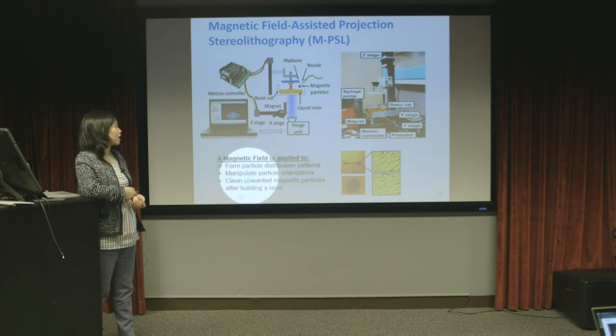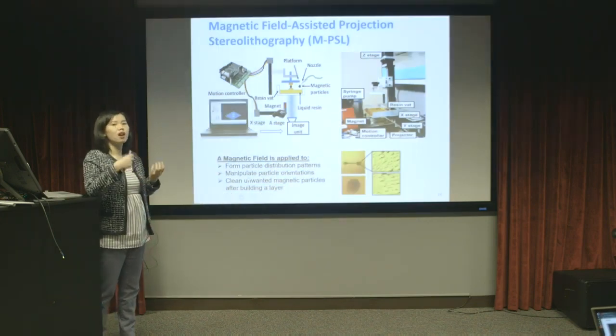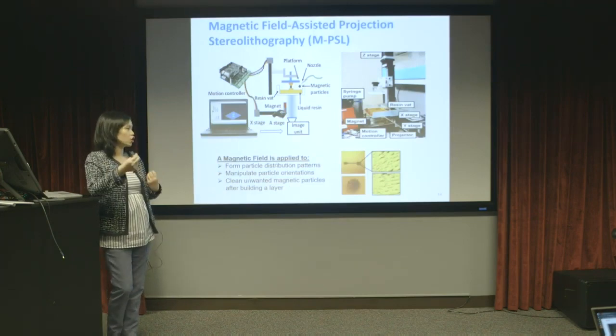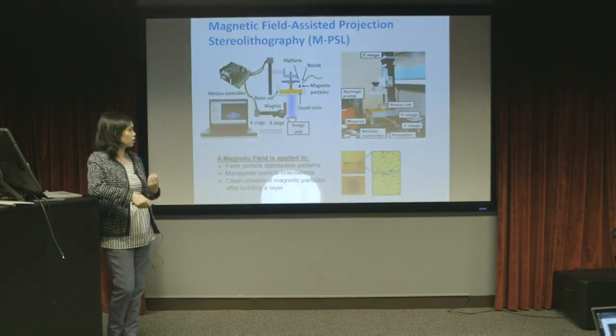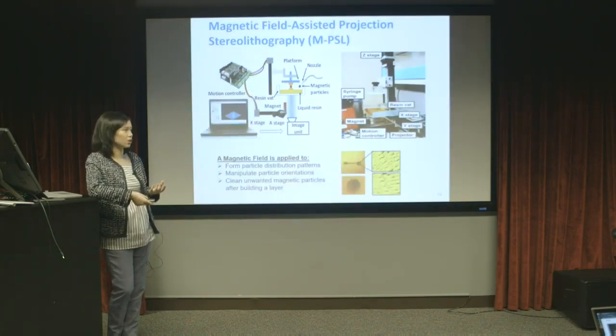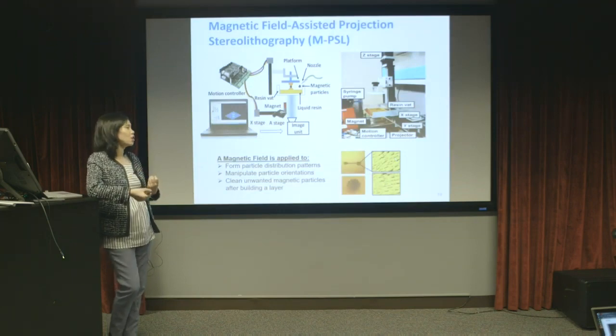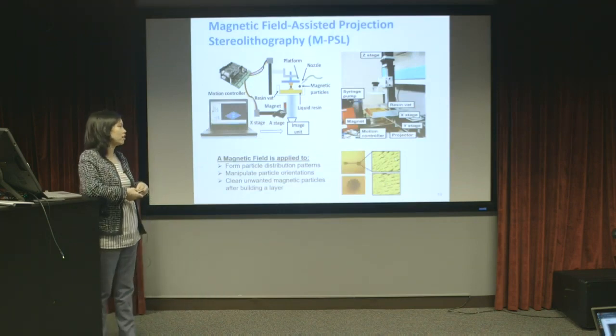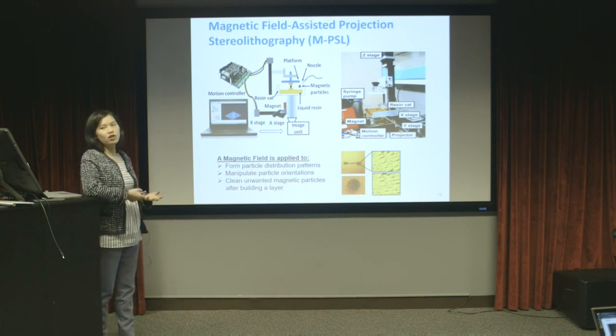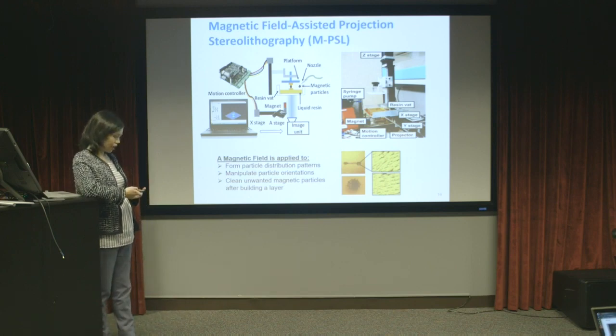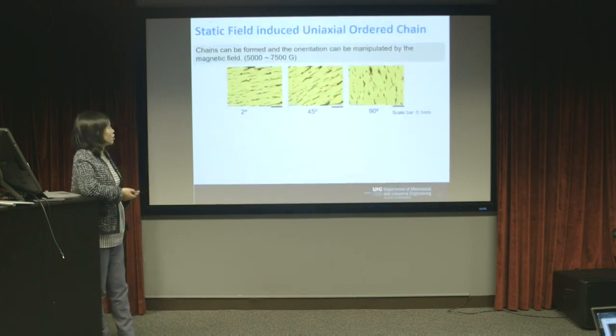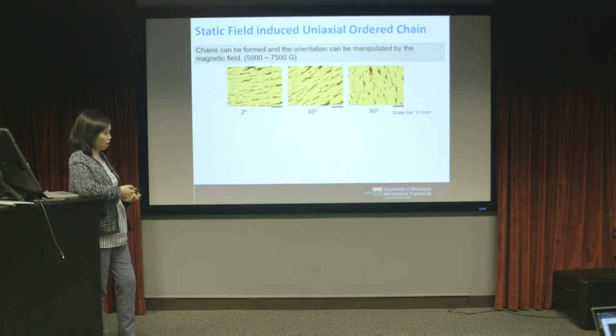So with an external magnetic field, we can form the particles into a chain structure like what is shown here. Initially, it's nano-sized or micron-sized particles, and with a magnetic field, you can assemble those particles into chain-like structures. And you can manipulate the particle chain orientation with the external magnetic field. We can form the chains with different dimensions and also different orientations as shown here.